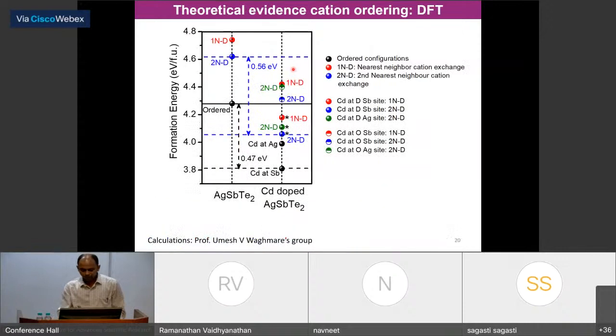So then, as usual, we talked with Umesh, and Umesh's group has shown formation energy calculations, and he showed that ordered AgSbTe2 has a stable structure compared to the disordered AgSbTe2 structure. But this ordering, the structure becomes more stable if I dope cadmium. So actually cadmium is creating ordering, and we have done many calculations to show that cadmium sits in the disordered Sb position in the compound, and this stabilizes the ordered structure. So Umesh has shown that our chemical intuition is actually true.